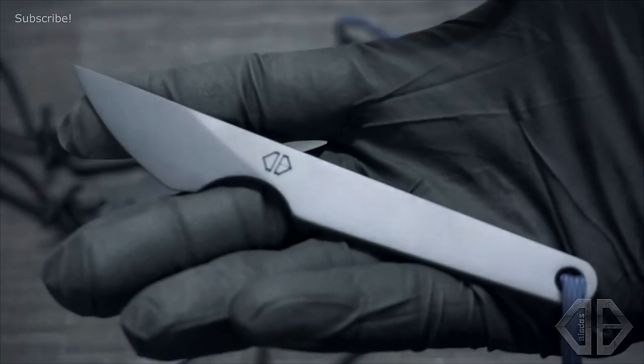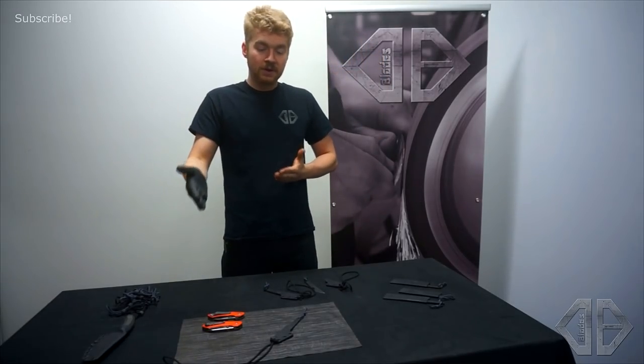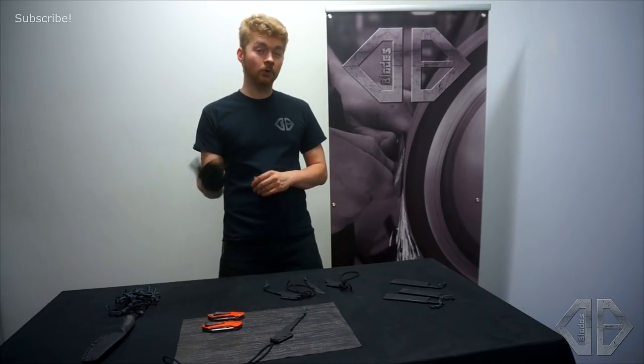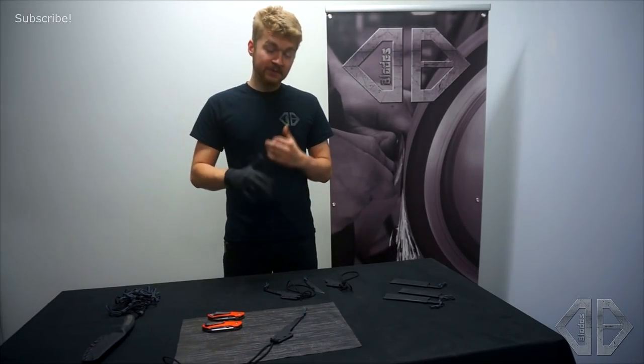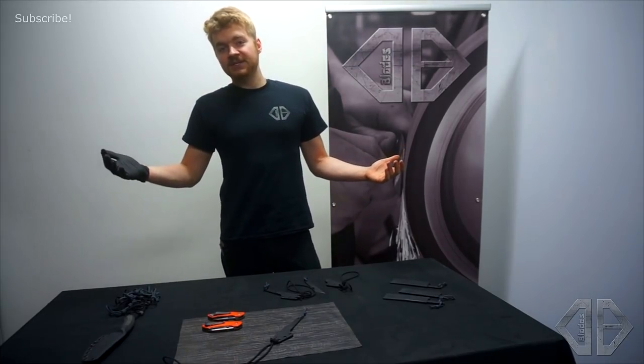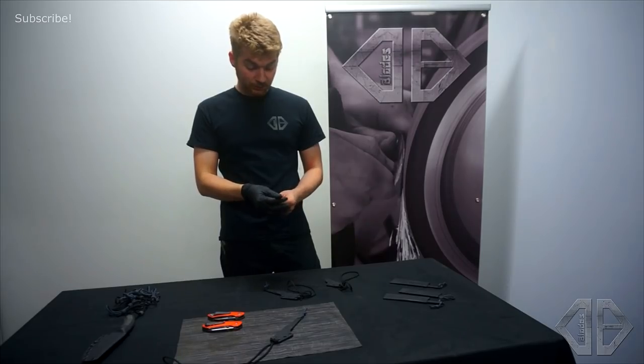I do the Surgeons with Elite Cerakote. According to Cerakote it is more impact resistant, more wear resistant, and a lot slipperier than regular Cerakote, which is great for these knives — just a little upgrade a few years ago to make them a better product. This batch and the next will be the last two in Nitro-V; in the future we move to probably D2. Nitro-V is rock-solid steel but the issue is it's a coil steel — it remembers how it was originally formed, and when you heat treat it, it has a tendency to warp and twist. Moving to D2 should make manufacturing easier, less straightening, and a lot of people prefer D2 for its wear resistance. With the coating you shouldn't have to worry about rust too much.